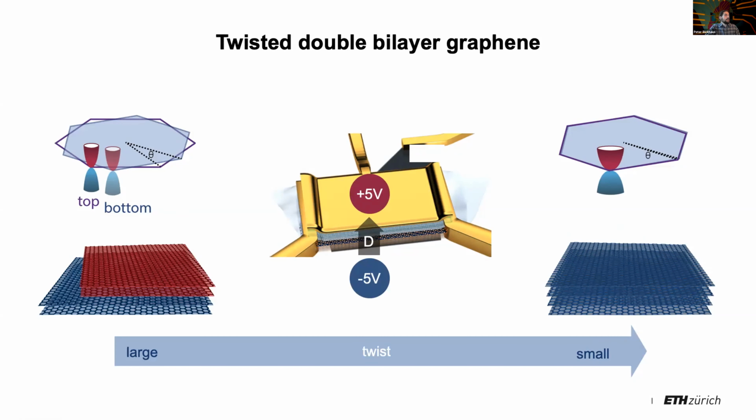So indeed, if one looks at Hartree-Fock calculations, and these calculations have been done by Yang Su and Alan MacDonald, if one puts these bands into the Hartree-Fock machinery, then you see that there's a gap opening here. So these dashed bands here are exactly these bands that you see here. They're not just put on top of each other. And you see with the correlations, which are the solid bands, there's a gap open. This gap opens by electron-electron interaction.